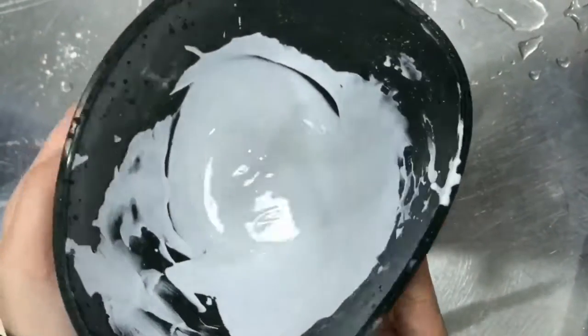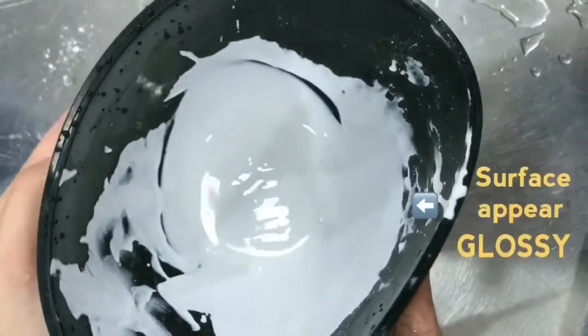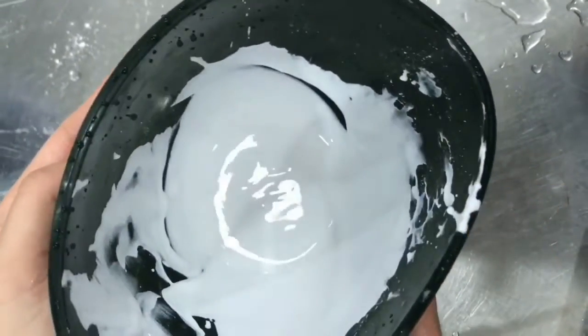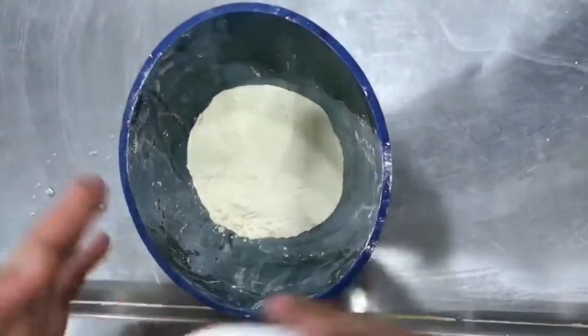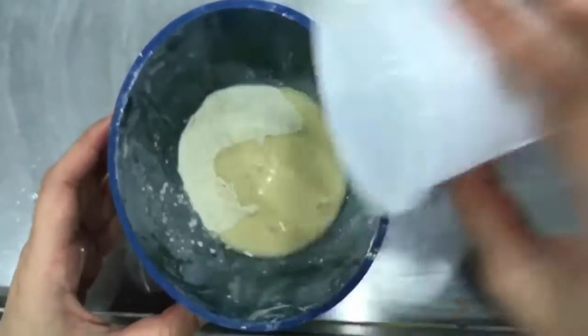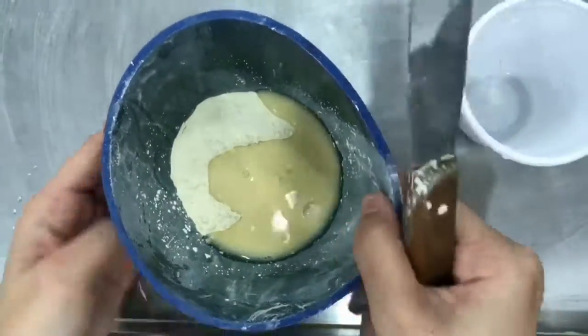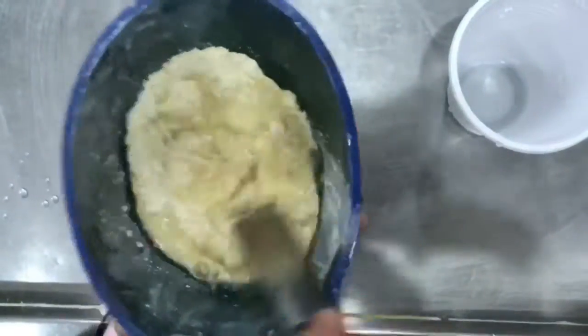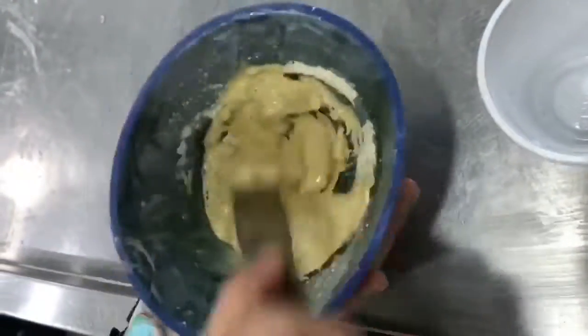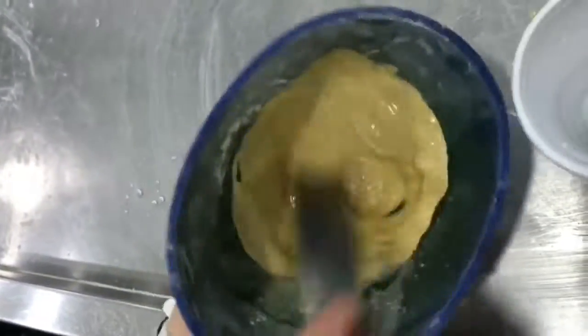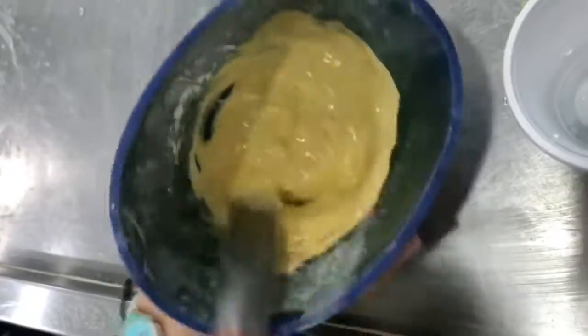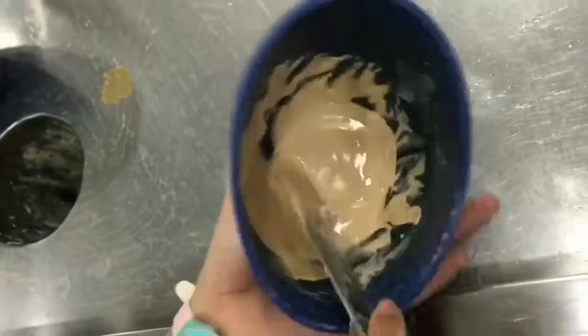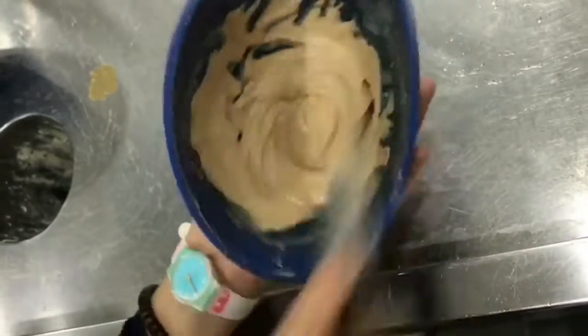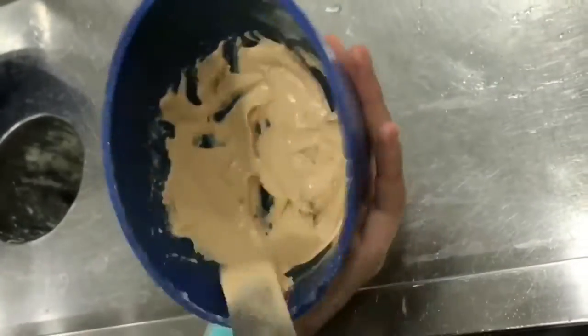As you can see, before it's set, the surface appears glossy. The mixing process for dental stone and dental stone with high strength and low expansion is the same as plaster of Paris, where we need to add water and powder together and mix them thoroughly using the spatula. Make sure that there's no air bubble trapped. For high strength stone, we need to measure accurately the amount of powder and liquid.